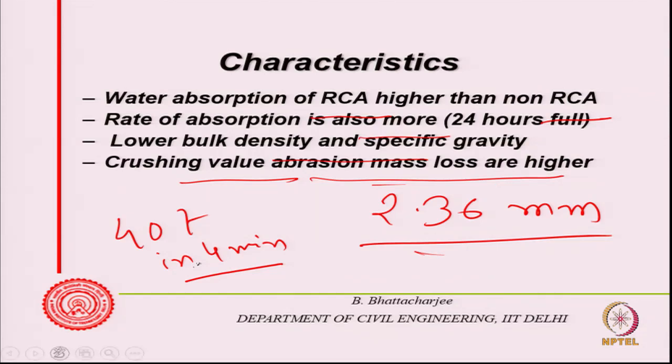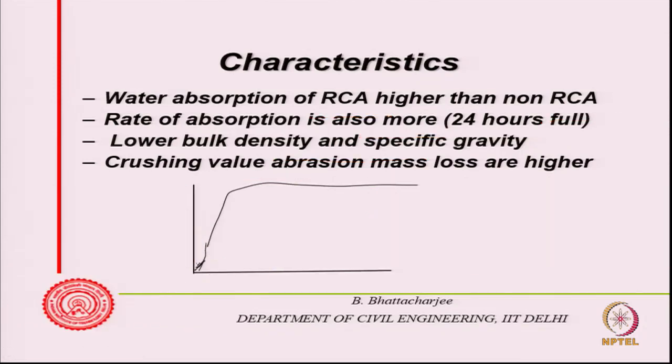So the recycled aggregate does not have the same kind of quality as our normal natural aggregate. So you have to use them judiciously. Now total absorption, if you look at it, time versus absorption, 80% comes in 10 minutes itself, and after that it remains more or less the same. Most of it gets absorbed very quickly.